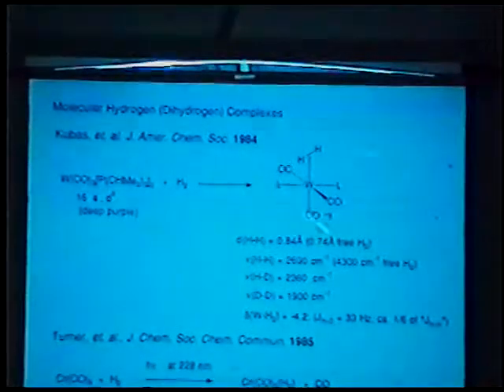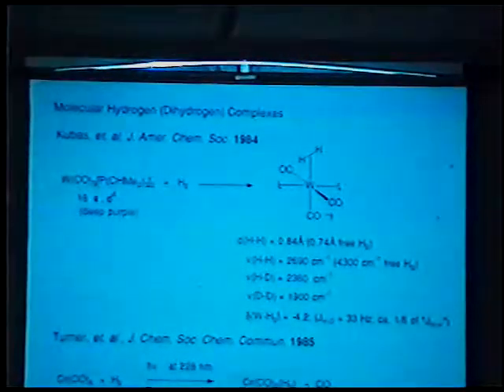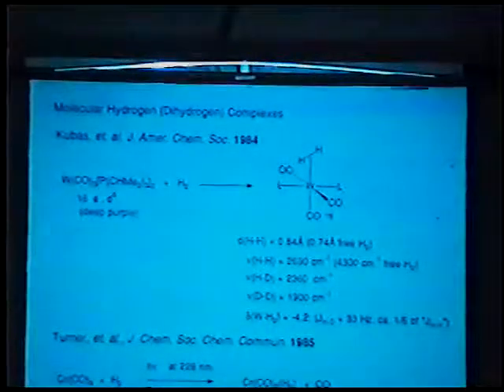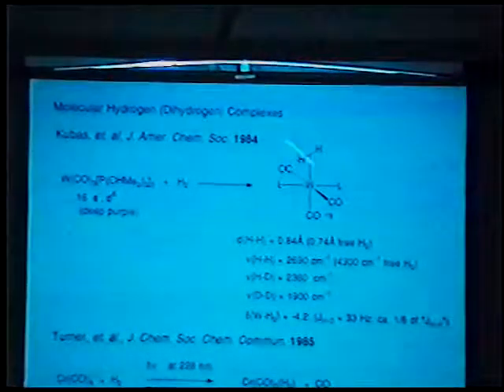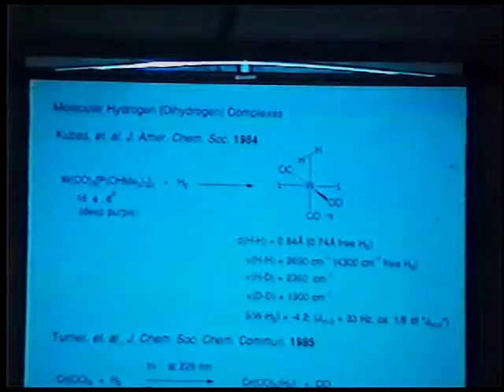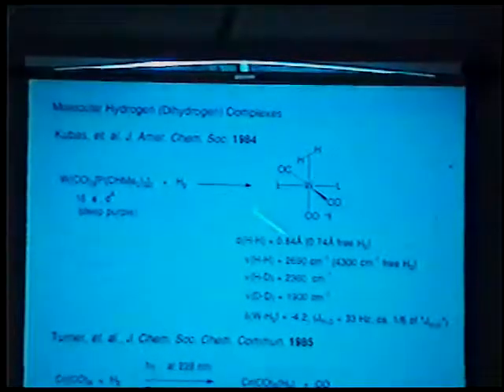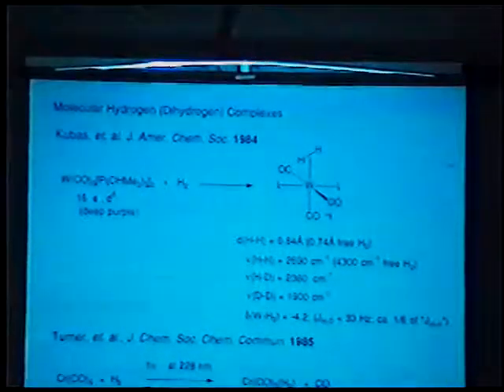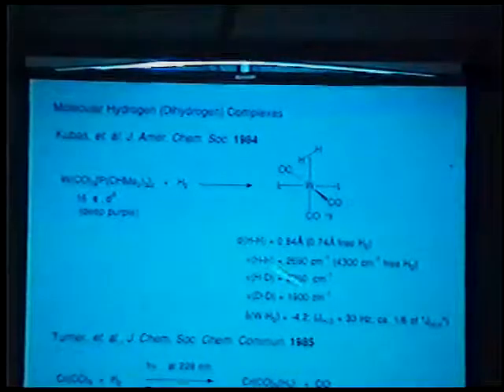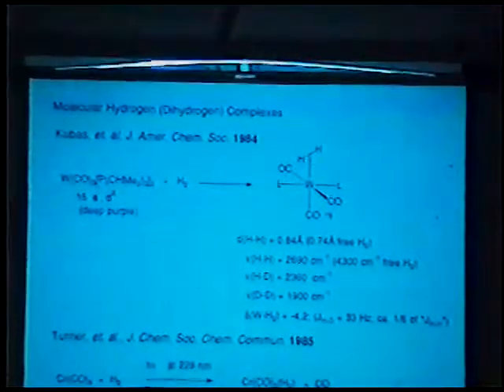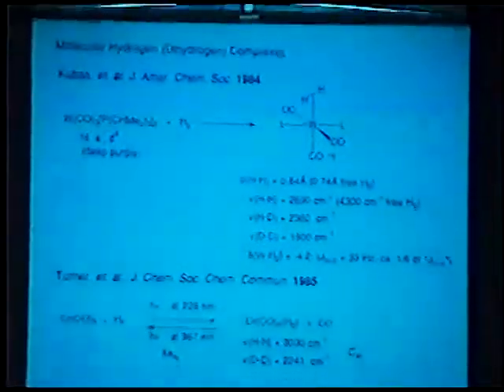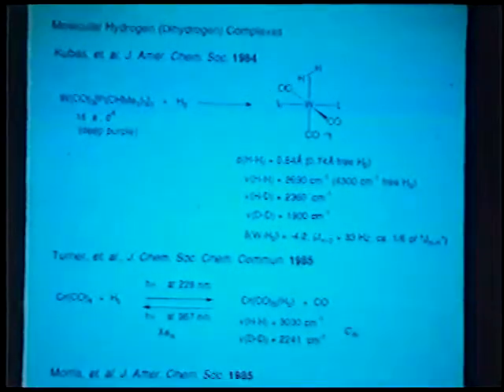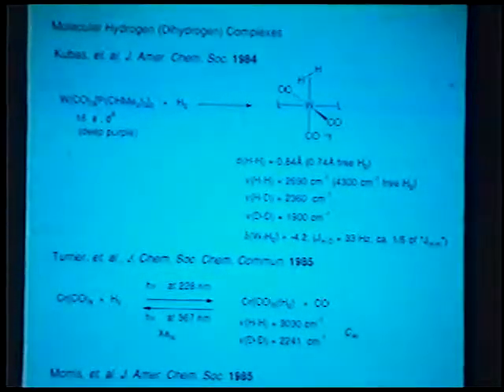Now these sigma complexes are really not all that unexpected, given the fact that Kubas has isolated analogous types of complexes as stable materials that can be examined by X-ray crystallography, neutron diffraction, and the like, where the HH bond of the dihydrogen molecule is intact. Only a tenth of an angstrom longer than that for H2. These have lower HH stretching frequencies, and they've been found in a number of cases now. I would say the number is growing daily almost, where one can identify what used to be thought to be a dihydride as in fact one of these dihydrogen complexes.